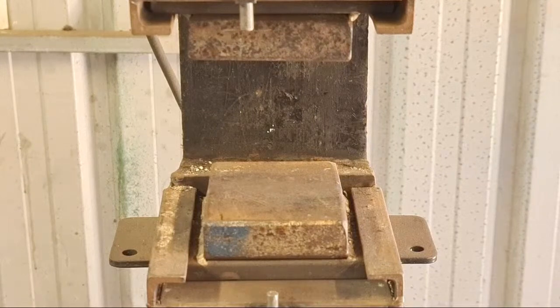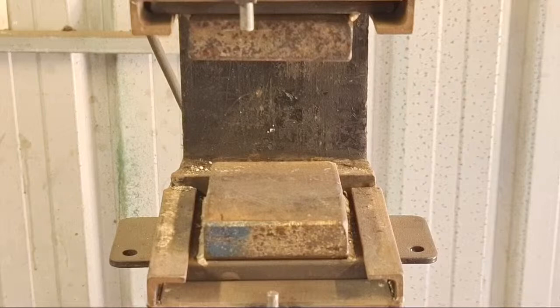1080 is fantastic to use. 1080 is a eutectoid steel, so it's right in the sweet spot. You can get pretty bendy, and that's because it's that medium carbon steel. It's that spring level of steel. It's very forgiving in the forge weld, and super forgiving in the heat treat. 1084, 1080, and 1085 are all eutectoid steels, or around the eutectic, so they're relatively easy to heat treat. Oil, definitely oil.